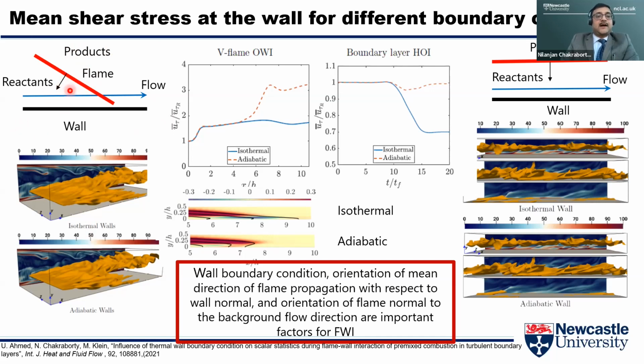In the case of V flame, this is the situation in a mean sense. Thermal expansion takes place mainly in the flame normal direction, which has a component in the mean flow direction, and that sets up a stronger velocity gradient. As a result, in the reacting condition, the friction velocity actually increases in comparison to the non-reacting case. And this trend is more prevalent in the adiabatic case because the flame does not quench, so the thermal expansion effects are stronger. However, in the case of head-on interaction, the friction velocity with respect to the non-reactive friction velocity decreases as the flame wall interaction takes place.